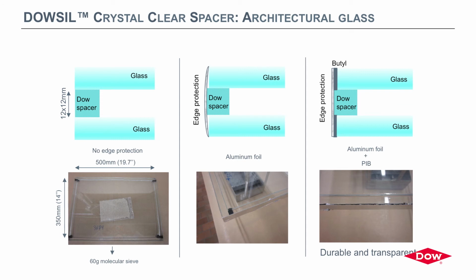This is R&D, right? In the next system, we have misaligned the Dow spacer with the edge of the glass. So you see it's a little bit out of it, and we stick on the edge a metallized foil, just to enhance protection of the spacer and to see if this metallized foil is going to improve the durability. As we know that silicones have some moisture vapor transmission. It's not the primary seal, right? So we want to understand that.